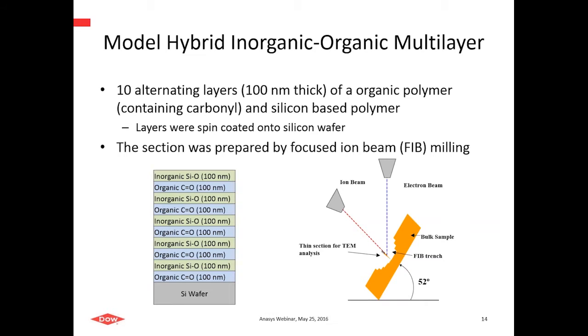So we thought we'd challenge the technique by preparing something with much finer layer thicknesses, and this was this multi-layer I mentioned earlier. And so this is a hybrid inorganic-organic layer. It's made by spin coating an organic polymer that has carbonyl functionality, and then a second layer, an inorganic with silicon-based chemistry. And these were spun coated as alternate layers. Here's a picture of the stack in the lower left on silicon, and then a little cartoon again of the focused ion beam milling that was used to mill a 300 nanometer thick section that was plucked and then set down on the surface for us to look at.